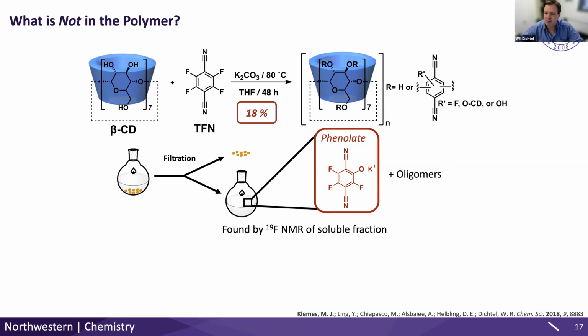He studied it very carefully in terms of the polymerization and a lot of other experiments that were complementary. And he found that there was this small side reaction where our Tfn crosslinker was sometimes incorporating an extra oxygen with a negative charge onto that structure during the polymerization. That side reaction was one of the reasons that we were getting a fairly low yield in the polymerization in the early days, which we have since solved.